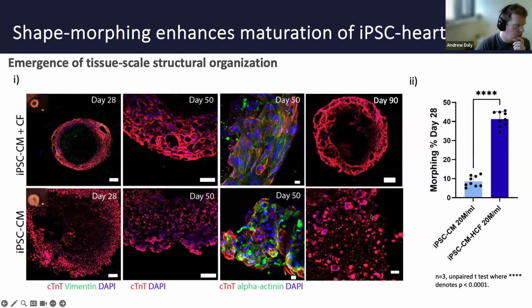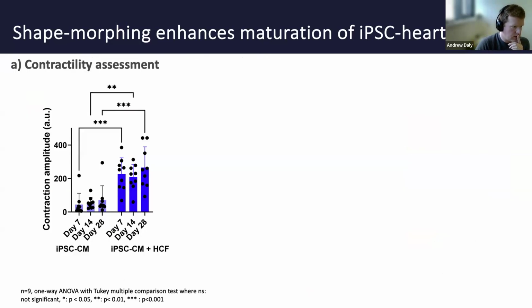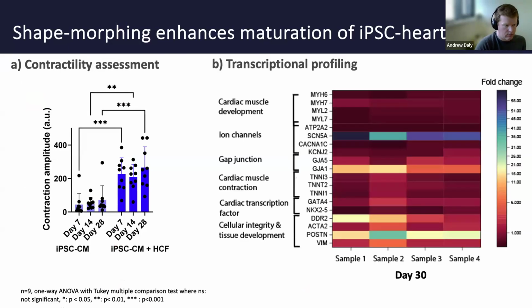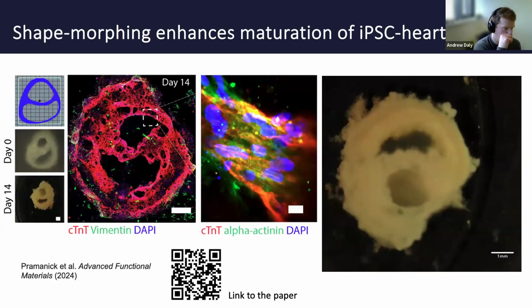So it's nice that we can improve the functionality of the tissue. We can quantify the intensity of that beating. So we get about a 4 to 5 times increase in contractile force when we have this morphing tissue. And again, we did some transcriptional assessment to look at the gene expression profiles. And again, there was upregulation of genes related to ion channels, which are important for propagating the electrical signal through the tissue.